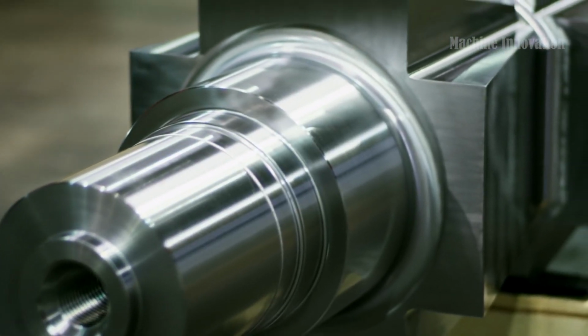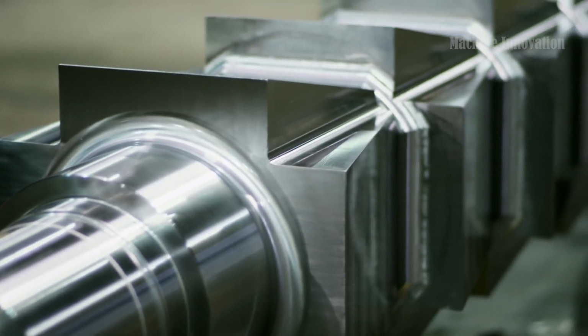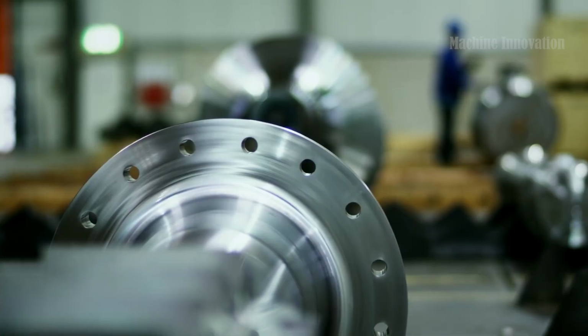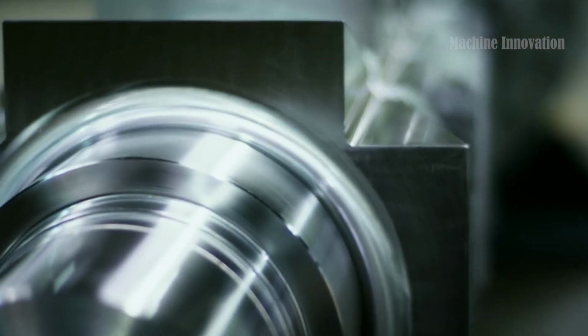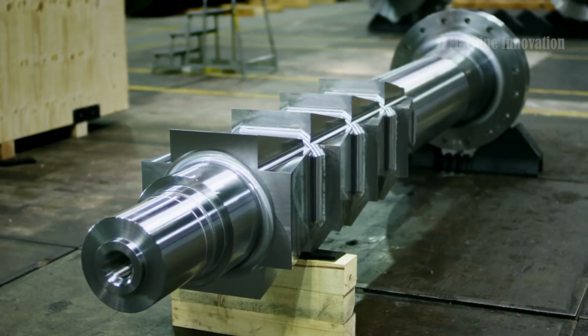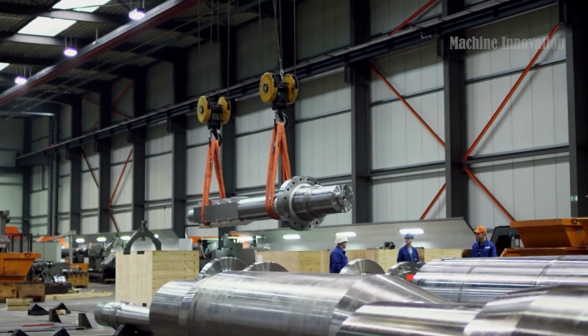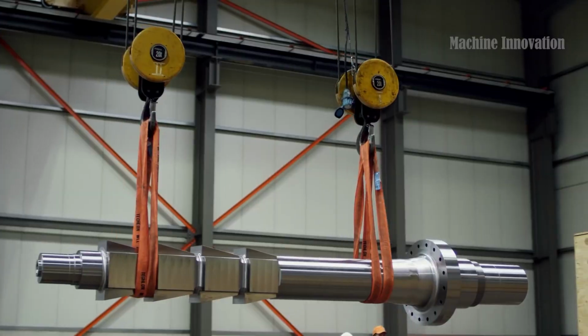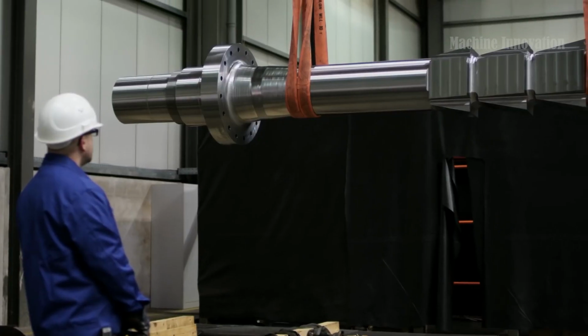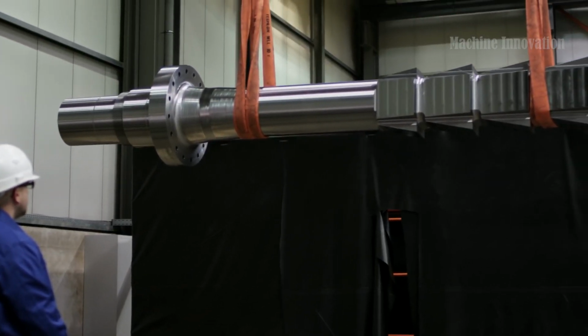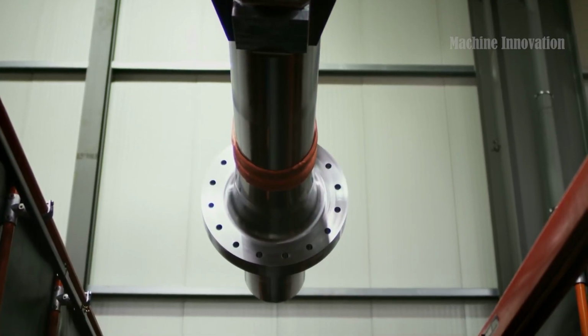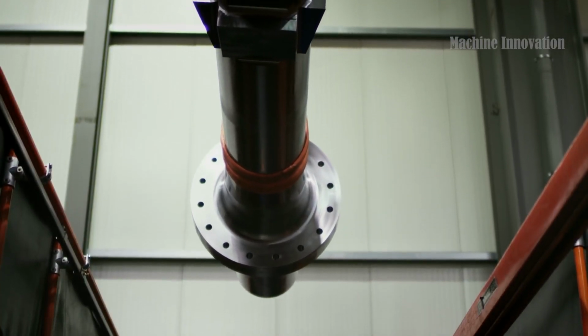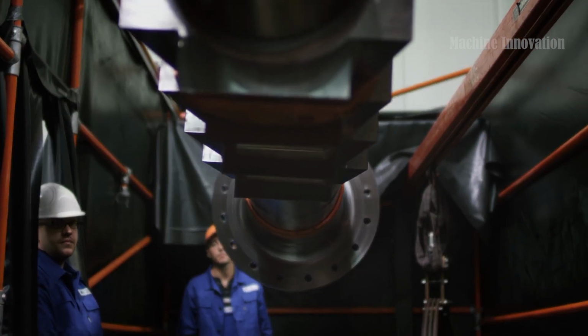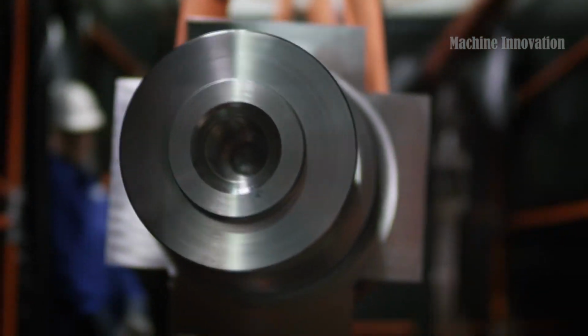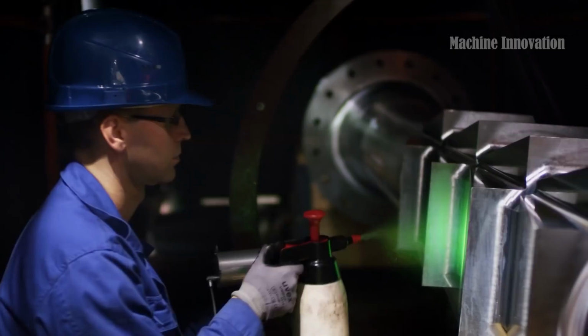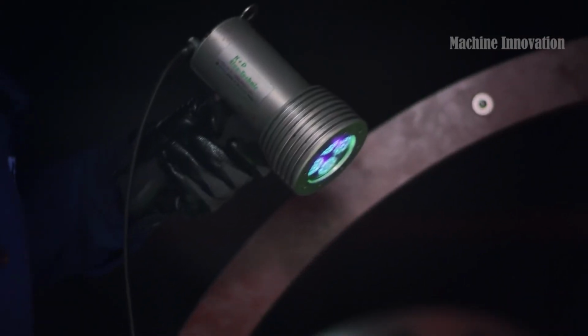Before the crankshaft is deemed ready for shipment, it undergoes thorough non-destructive testing, NDT, which includes techniques like magnetic particle testing, MP, to detect any surface or subsurface defects that could compromise the integrity of the crankshaft. NDT ensures that no cracks, voids, or other flaws are present that could lead to failure under operational stress. This step is critical for verifying the safety and reliability of the crankshaft without causing any damage to the component.